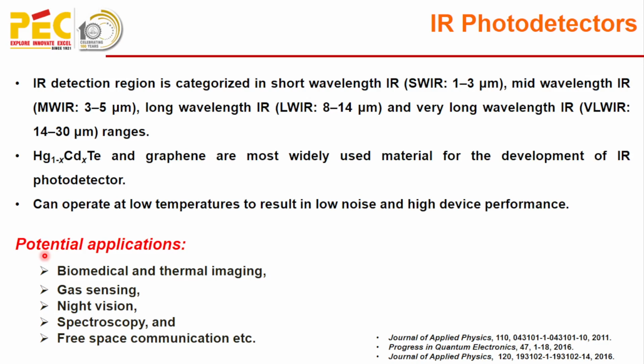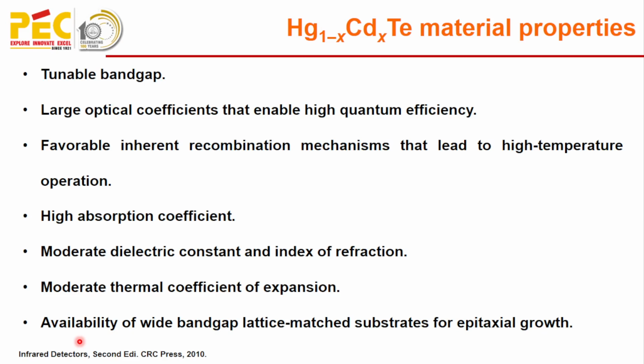So, mercury cadmium telluride is most commonly used for making IR detectors because it has a tunable band gap. It has a large optical coefficient which will enable high quantum efficiency. It has a favorable inherent recombination mechanism that will lead to high temperature operation. It has a high absorption coefficient. It has a moderate dielectric constant and index of refraction, moderate thermal coefficient of expansion, and availability of wide band gap lattice matched substrate for the epitaxial growth. So these properties make mercury cadmium telluride a suitable candidate for the IR detector.